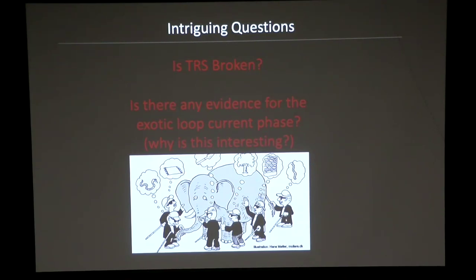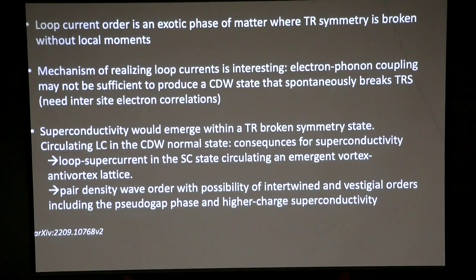So one question you can ask, since you've heard me go on and on about broken time reversal symmetry, is why are we interested in this exotic loop current phase? What are the consequences? There are actually many consequences of having this exotic phase. One thing is, it tells you something important about the material itself. It tells you that correlations might be important in having the CDW. But more importantly, remember, this is a superconductor, and it's a superconductor that arises way below the charge density wave transition temperature. That means that if time reversal symmetry were broken, the superconductor arises within a broken time reversal symmetric phase. So that must have consequences for superconductivity.